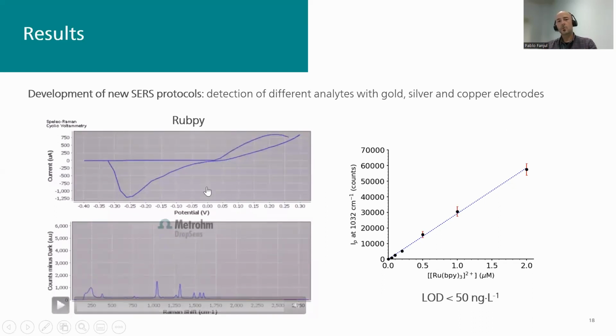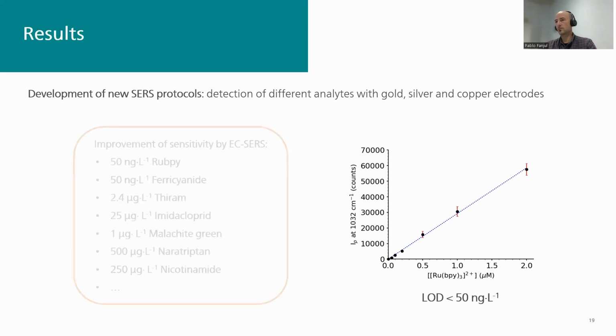Okay, so following this methodology and having different concentrations of ruthenium bipyridine in solution, we were able to detect this molecule with limits of detection below 50 ppt, parts per trillion. So it means that this Raman with a SERS effect is really sensitive.